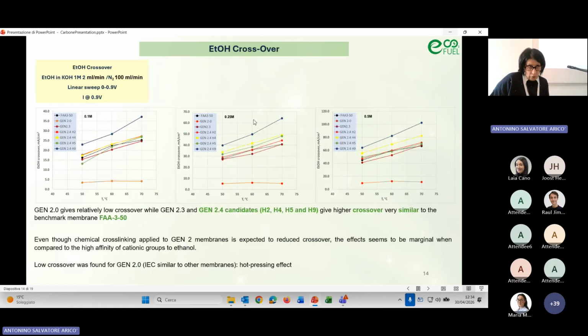Then we also studied the ethanol crossover in the same configuration as the hydrogen crossover, but only feeding ethanol solution in KOH 1 molar, with different concentrations of ethanol, because these concentrations were estimated according to the results that we obtained in the real operation. So we can see that with the membranes, except for the H2 membrane, all the membranes have a little bit higher crossover than the target of the project, that was 10 milliampere per square centimeter. The reason why the H2 has this very low ethanol crossover was because this membrane was hot pressed due to the inhomogeneity in the thickness. So the hot pressing helps to compact the membrane and helps to reduce the ethanol crossover.